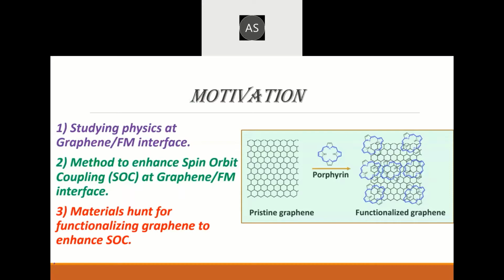And the molecule, or the organic route that we have chosen for this, is a molecule called porphyrin. The idea behind choosing porphyrin was that this ring can be doped with a heavy metal in the center of it. We have chosen platinum as the heavy metal. You can also have tantalum or tungsten in the center of this porphyrin ring, and then you can functionalize your pristine graphene using a spin coating method and some heat treatment to activate this porphyrin doping on top of your pristine graphene. So this is how we have started.